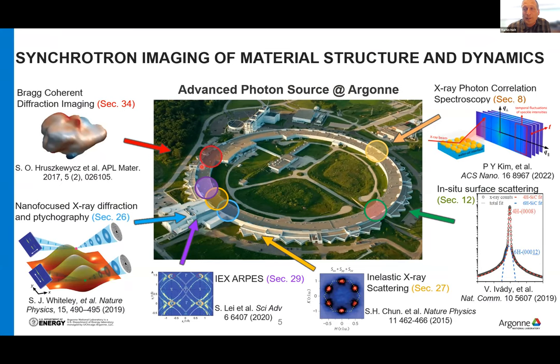I'm just pulling out the things that I thought would be most relevant. As Dylan was talking about as well, you can use Bragg coherent diffraction imaging to resolve 3D structures and paint structural information onto them in real space. And we do similar work with nano-focused hard X-rays. It's more of a scanning probe approach that's suitable for extended samples in more complex environments. And both of these rely on the fundamental sensitivity of the light to the structural perturbations.